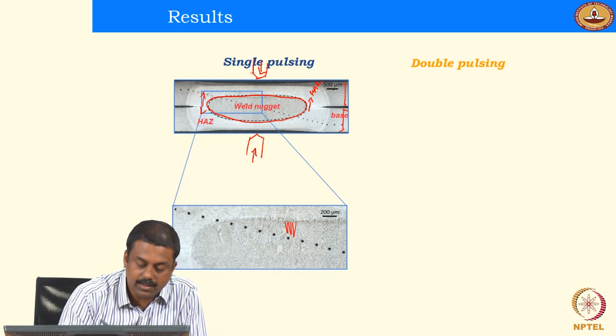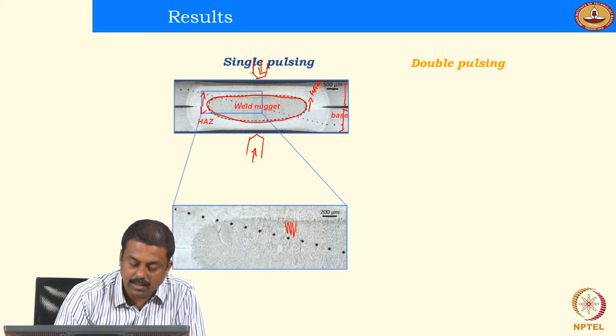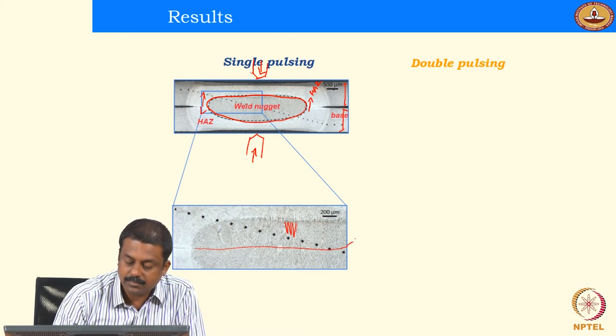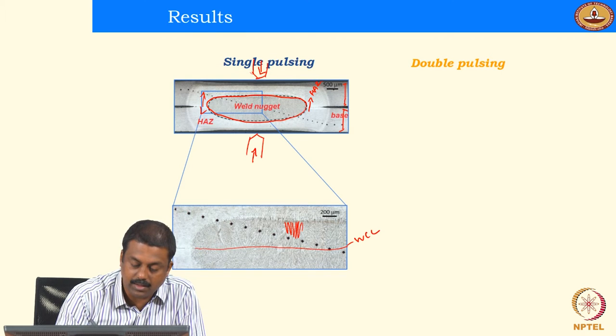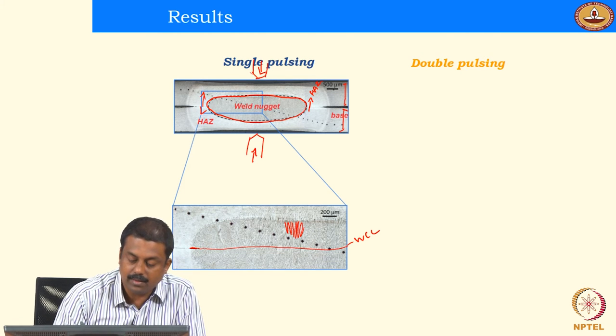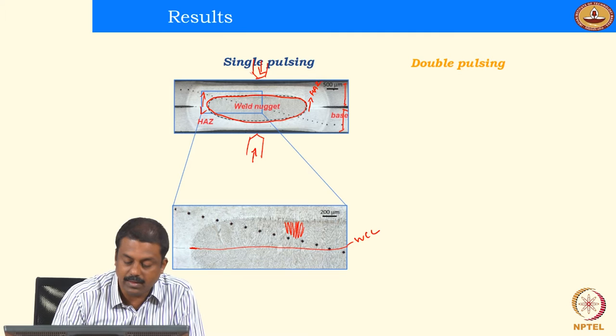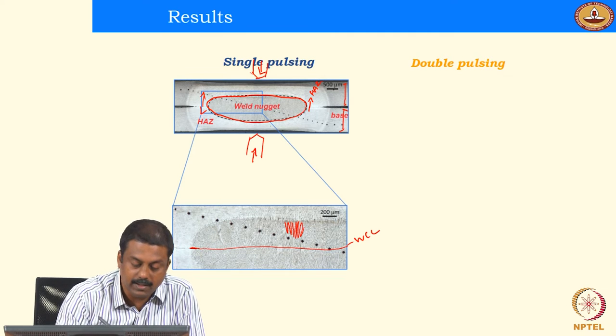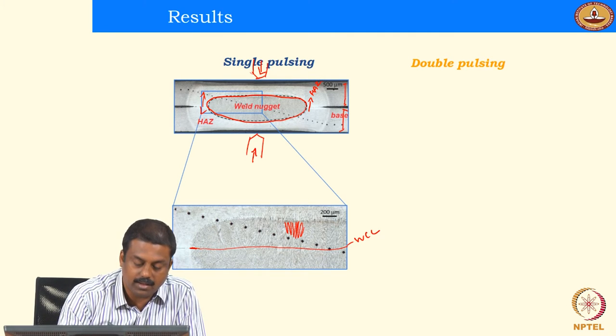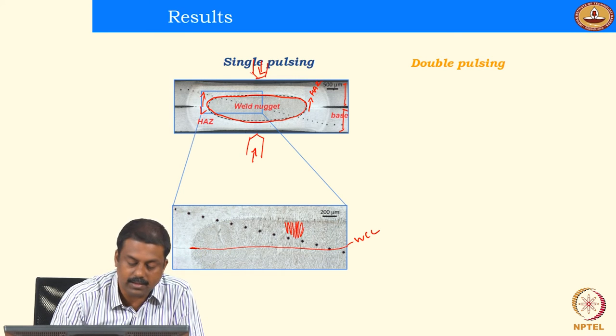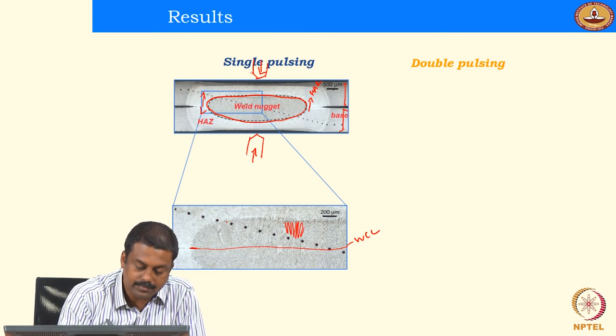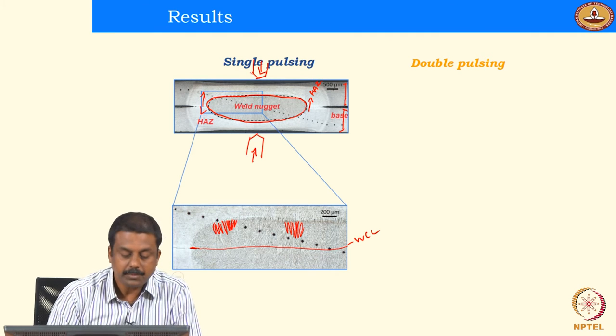And during this process, the alloying elements are trying to segregate at the weld center line, because that is the region which solidifies at the last, right? So, when the grains are solidifying from this direction, you will have a segregation at the weld center line. Because the solidification of this liquid over here takes place at the end, and the alloying elements such as carbon, phosphorus would be migrating towards the weld center line when the solidification happens from the fusion boundary.